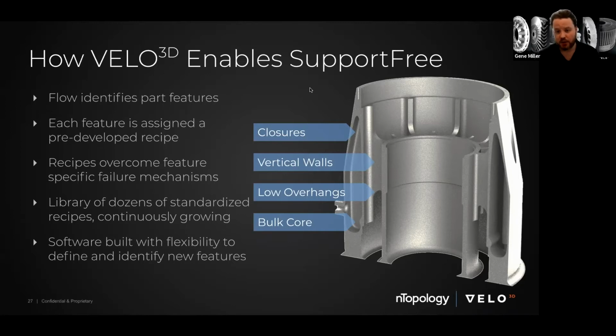In this case, for this part, we have certain geometries like closures. There are tall vertical walls. There are some low overhanging features that go below 45 degrees or even near 0 degrees. And then there's also some bulk core where you really want a specific laser parameter to put down as much material as quickly as possible to enhance your print time. This discretization of laser parameters really helps us achieve otherwise unprintable geometries and still be competitive as far as throughput.